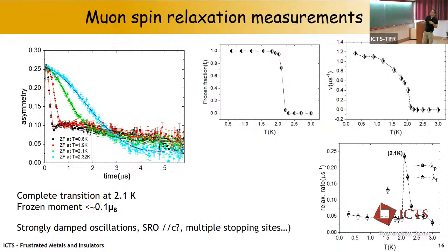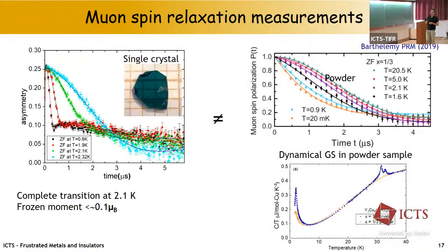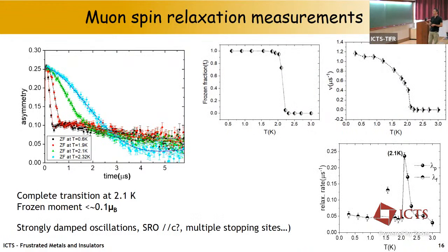We have a bit of change of the dynamics a bit above 2.1 Kelvin. That's in zero field. So I think the correlation really starts below 5 Kelvin, and on top of that, you have the effect of the external field, yes, indeed. Oh, I see. But the muon relaxation rate had a very sharp peak at 2 K. It's much sharper in zero field, yes. Okay. Thank you very much.